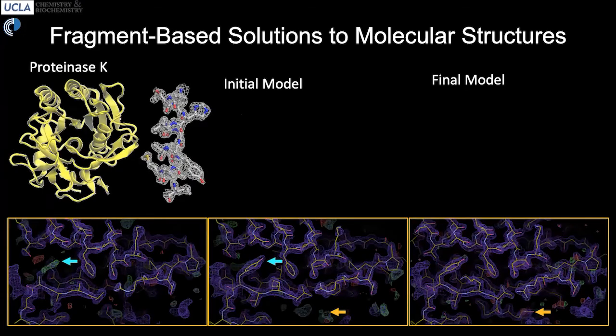And so in our group, we've already started doing that, and we're excited to incorporate newer models for structure prediction into pipelines that will ultimately serve as a hybrid space where you can validate a predicted model by comparing it to the measured crystallographic data acquired by electron diffraction, and then sort of shortcut your way to a solution where the data may not be ideal and may not give you a structure ab initio, but could corroborate the predicted structure pretty faithfully. And so we've done this with large proteins like proteinase K.